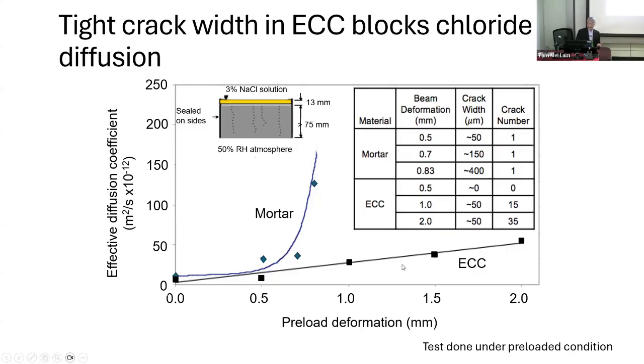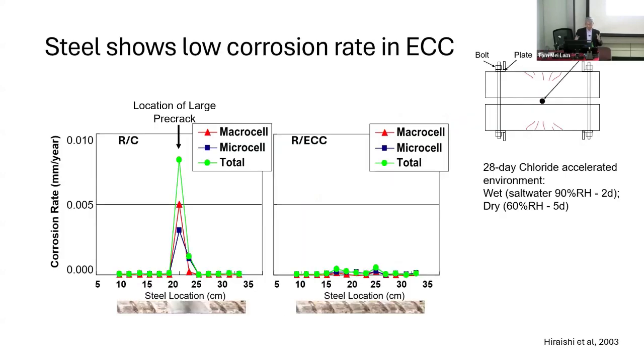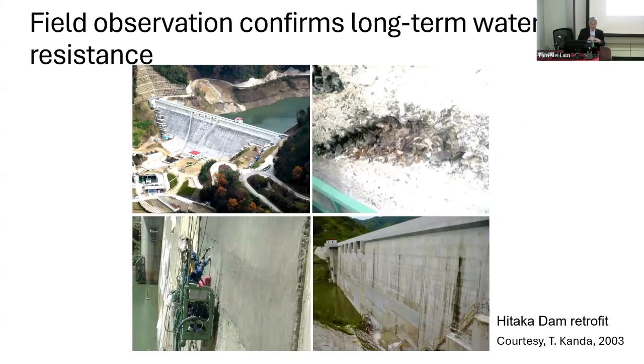And this is because as you increase the load and cause larger and larger deformation, the crack number increases, but the crack width stays constant. You saw that a moment ago. Crack width, despite large deformation, remains low in ECC. That's an intrinsic property. Okay, so these two test curves are demonstrating in the laboratory, simulating field conditions, the reason why ECC can be very durable for infrastructures. Okay, so let me jump to real life applications.